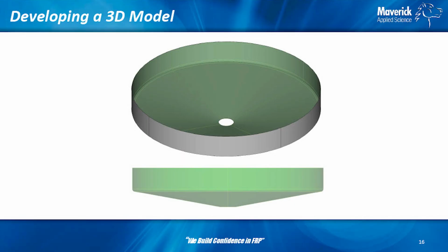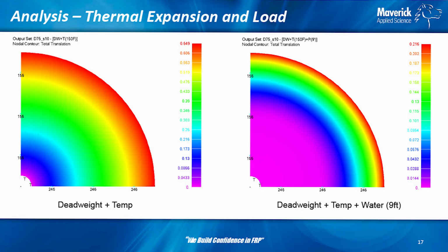So we took that, we modeled it, we looked at it at different diameters and levels of liquid. And so here we have it. This is empty, and this is with 9 foot of liquid. When it's empty, I showed you all that thermal expansion here. By the time it gets to the outside edge and it's hitting that corner, it's expanding, approaching 3/4 of an inch. When we start to put the liquid loads on it, because we've worked out friction factors, that liquid is helping us. We find that the liquid has reduced it from almost 3/4 of an inch to less than 1/4 inch. So that's the amount of engineering required to go into this kind of process.